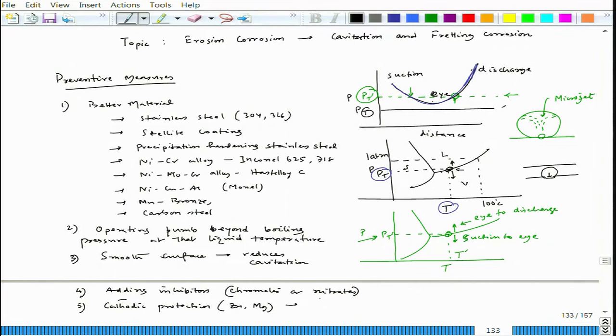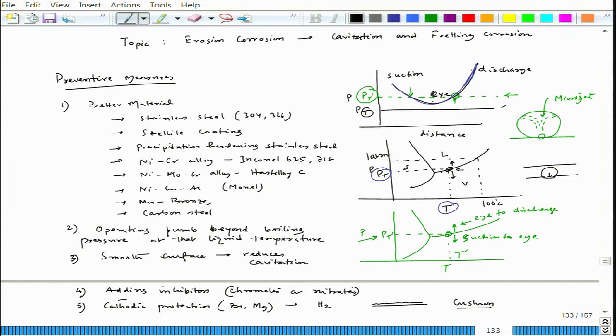In cathodic protection, if the cathodic reaction product is hydrogen gas, that hydrogen gas on the surface creates a cushion for the collapsing bubbles. When those bubbles burst, the resulting shock waves can be absorbed to a great extent by that cushion of hydrogen gas forming as the cathodic reaction product. This is one way to prevent cavitation damage.